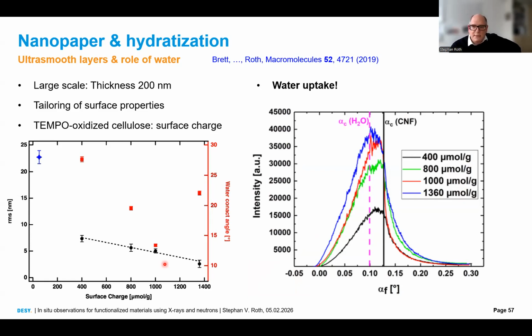And actually this graph here shows that even with X-rays, we can detect water. Remember what I said about the Yoneda peak. This Yoneda peak occurs at the critical angle of the material. The critical angle is proportional to the square root of the density. And this is this vertical cut from the GISAXS images. And you see here, this is the critical angle of CNF. And we see here something else. This cannot be the silicon substrate. The silicon substrate would show up here.